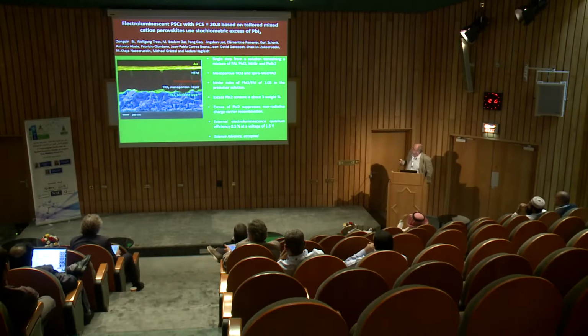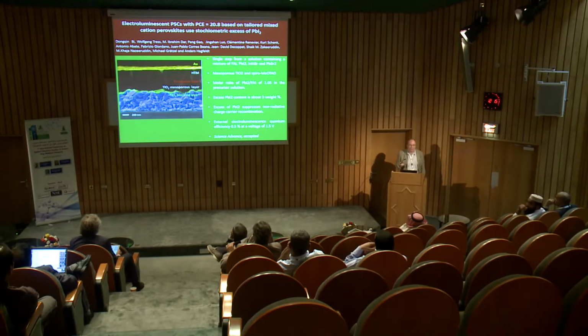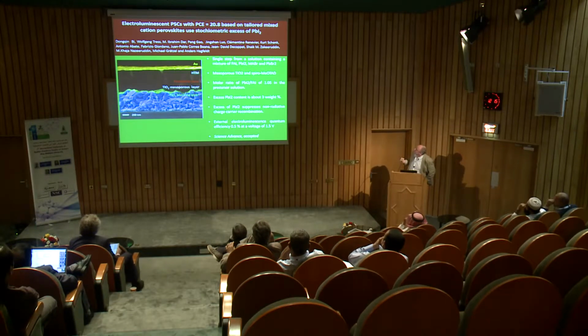And here is our most recent result. It's now accepted in Science Advances since a week ago. It's 20.8% in the lab and certified at 19.9% efficiency. So we do this mixed perovskite. We have still a thin layer of mesoporous TiO2. The spiro-OMeTAD is the hole conductor used here.